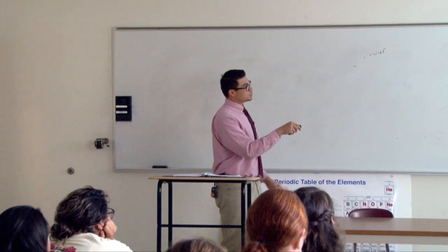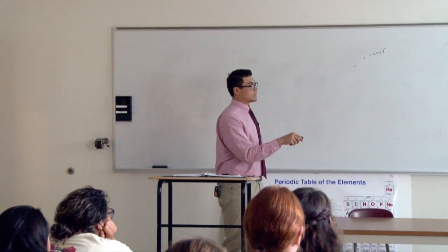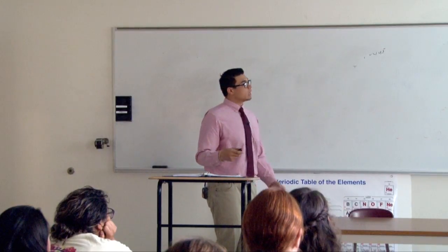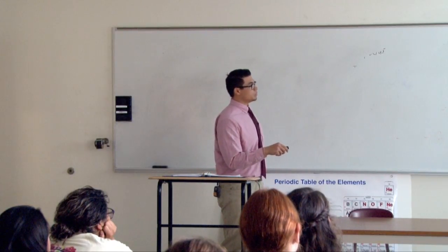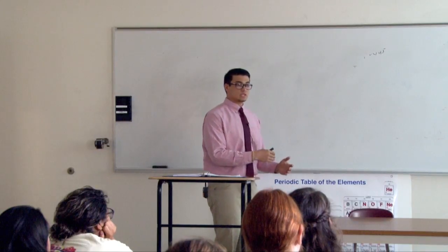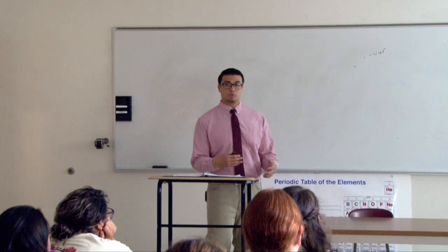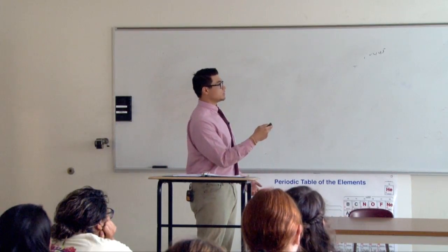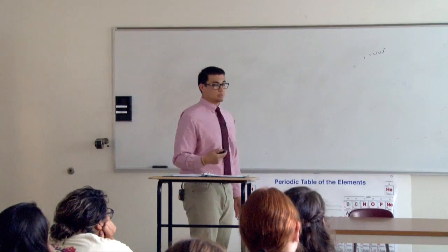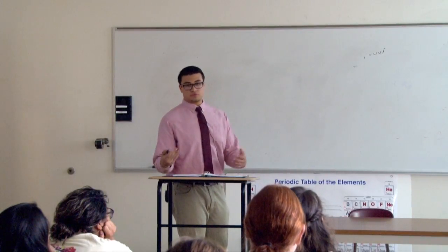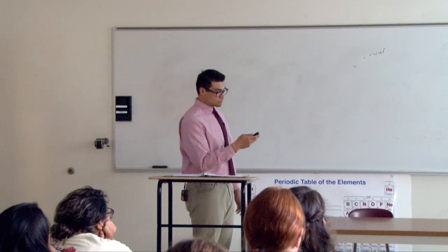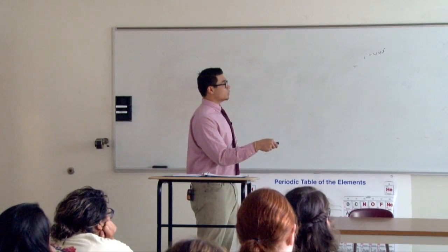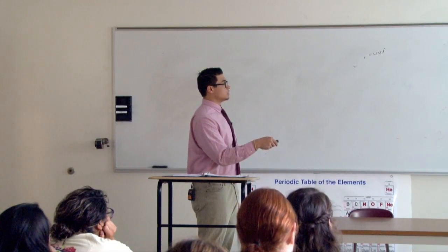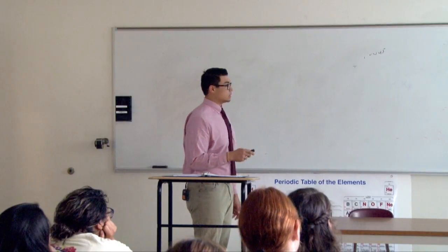But as temperature increases, we can also see the viscosity will decrease. But in general, we want to keep with the 1-ethyl, 1-butyl, because if we can start with low viscosity and a low melting point, it proves to be more efficient than starting with this 1-octyl, but then I have to raise the temperature by an extra 100 degrees. We prefer not to do that, but it is possible. So in comparison, we want to work with these ionic liquid groups and maybe even the 1-butyl groups as well.